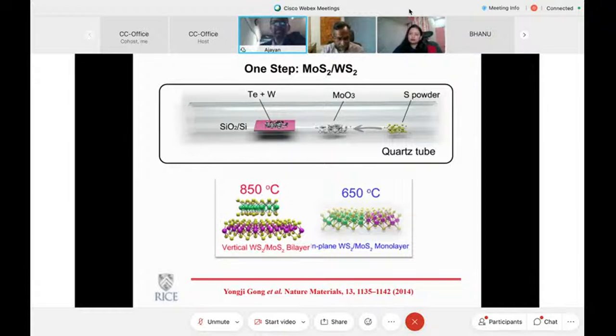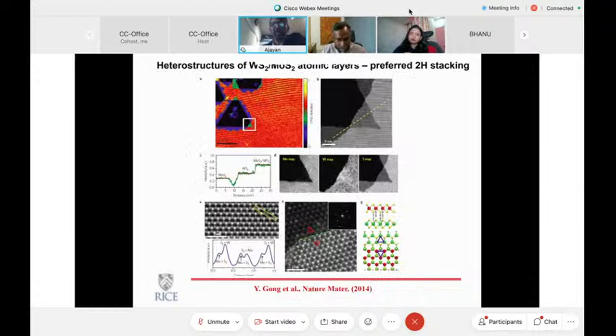And what we realize is that you can play with temperature to increase the yield of one or the other. So at higher temperature, it looks like there is a strong segregation and these layers seem to stack one on top of the other. At lower temperature, you start to see a mixed system where there is both in-plane and stacked sequences. And of course, we have to do a lot of microscopy. And of course, you can also standardize some spectroscopy techniques to understand what kind of stack is formed. And we realize that under certain conditions, you can optimize a preferred 2H stacking. Again, you can refer to this paper where we have published all the details of how the stacking occurs.